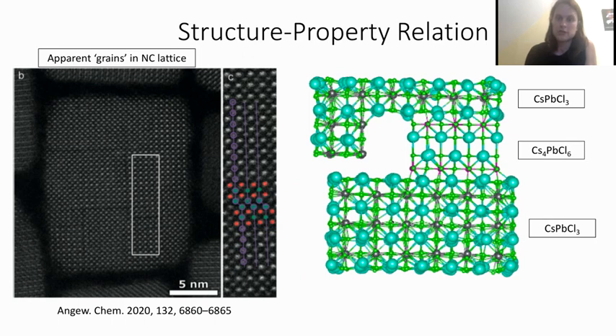And then on the right is just some playing around with seeing if it would be possible to get some sort of lattice or to atomistically model these Ruddlesden-Popper defects in a big enough nanocrystal. And this is just initial attempts, but it does seem possible where if you follow from the bottom, you follow the big blue dots, which are cesium. They go through the crystal, and then once they hit this subphase, they take kind of a diagonal and then go vertical. So it kind of matches the lattice patterns found from those high resolution TEM.